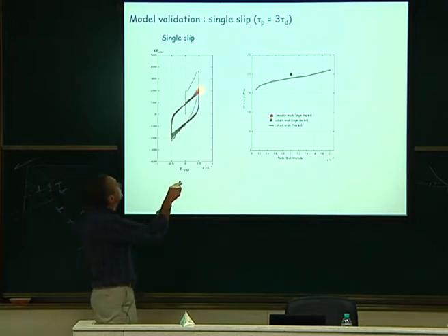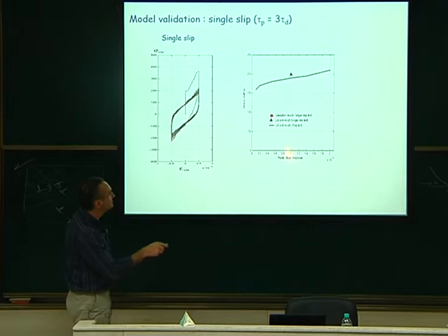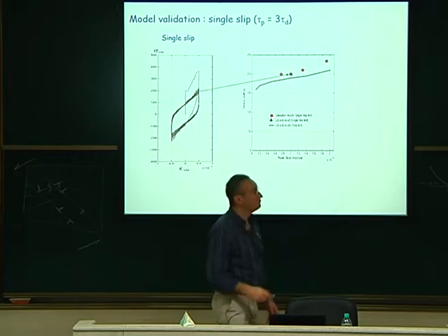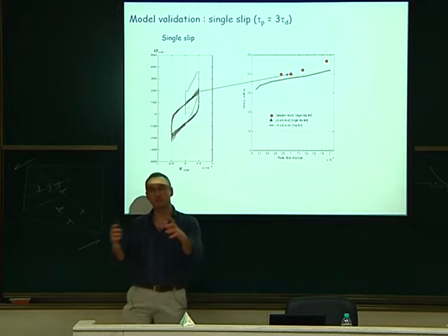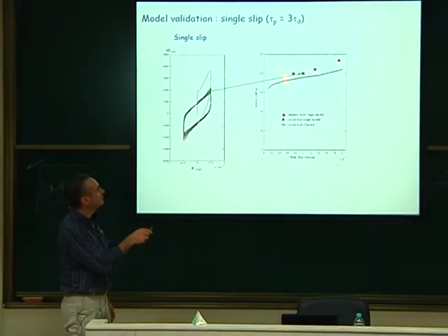If you pick out this value here, 200 megapascal, you plot it here. It compares very well with these experiments from Lee and Laird in the single crystal for the same load conditions, same strain amplitude. And we did more from that. For example, we tested more and more, and these are the DD points we found if you change the plastic strain amplitude. In DD, it's very easy to change that. In experiments, it's more complicated. So here we have 4 simulations.